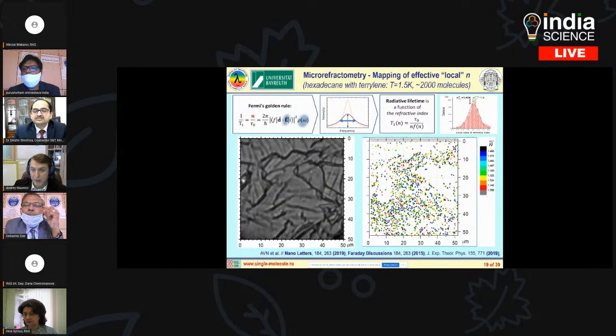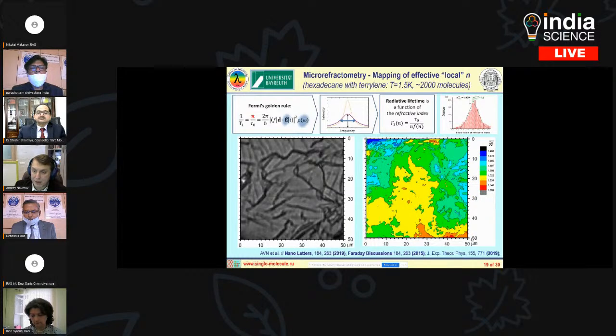So, for example, recently we realized a very specific technique for microrefractometry, because it's very important to understand the material characteristics on a sub-micrometer scale. You see, this is a molecular crystal, frozen hexadecane, and we put a few thousand label molecules inside of this sample. We find the spectral parameters of these molecules, depending on the temperature and the laser excitation power. Then we can recalculate the spectral parameters to the effective refractive index value. Then we can map the distribution of this effective refractive index value within our sample, and we can do this on the sub-micrometer level.